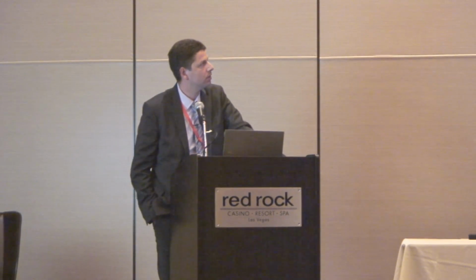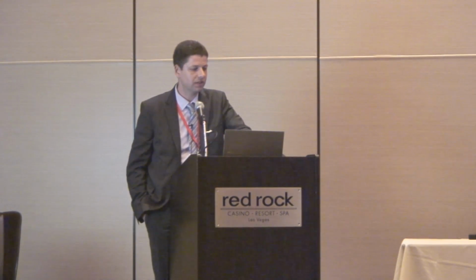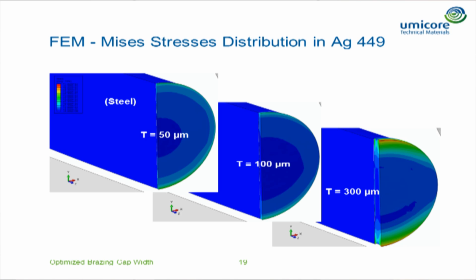Now we have a look into the Mises stresses inside the brazing alloy layer, and we can see that we have higher, a little bit more green color, higher stresses at the 50 microns, then at the thicker layer decreasing, and then when it's getting bigger again, it's increasing.